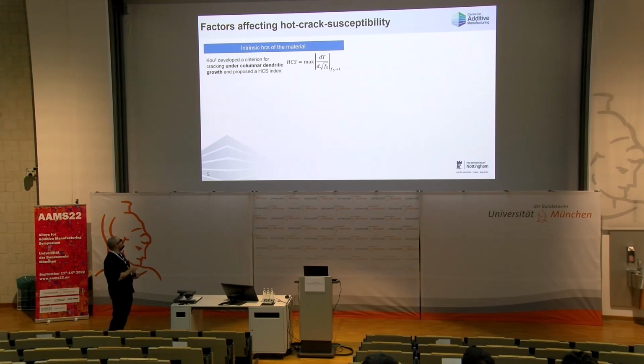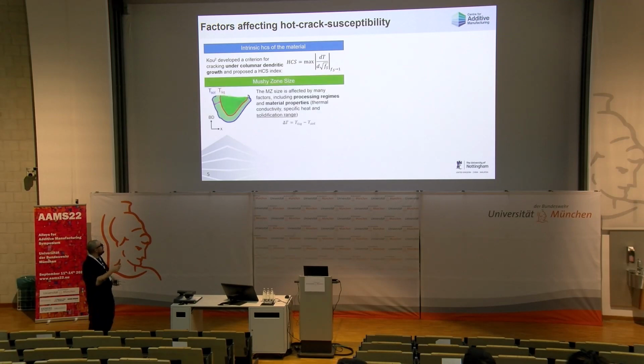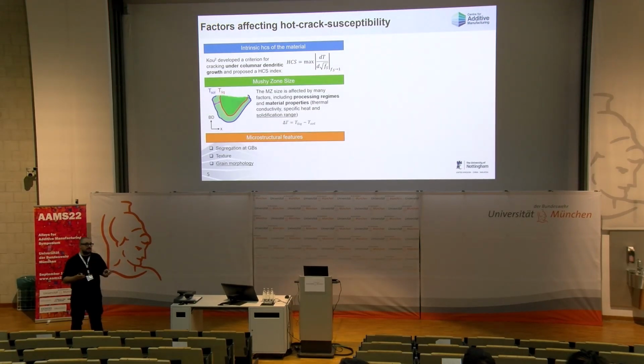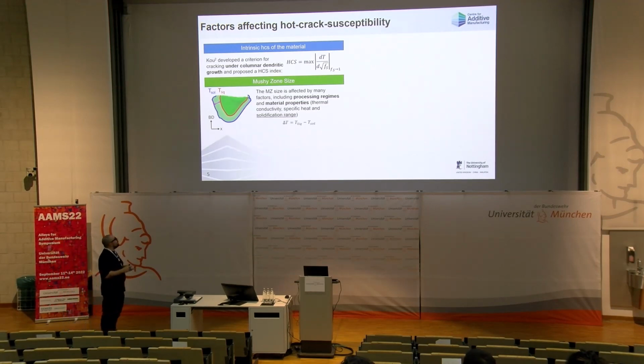proposed as a criterion by Kou a few years ago. It is widely used in the L-PBF community to assess the hot crack susceptibility of a given material. But there is actually more to this, because what we found out investigating also process parameters and stability of hot cracking as a function of process parameters is that there are other factors. One of these is mushy zone size. The concept is that when you have a larger mushy zone, it's harder for the liquid to backfill the crack.